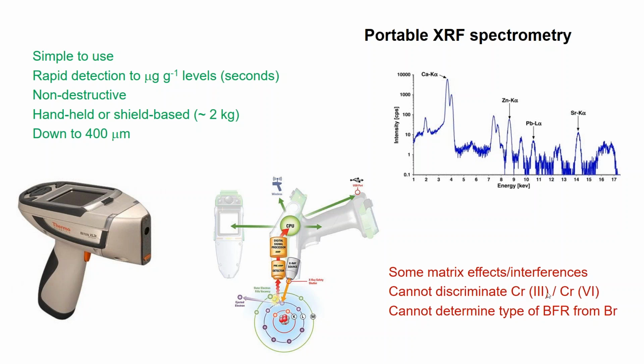So chromium-3 is perfectly safe. Chromium-6 is very harmful. So X-ray fluorescence will tell you there's chromium there, but it won't tell you which one. And it's chromium-6 in the RoHS directives which is most important. And it also can't tell you the type of brominated flame retardants. It can tell you there's bromine there, but it won't tell you what type of bromine. And that's a limitation of an assumption, and we sometimes have to consider or assume the worst case scenario.